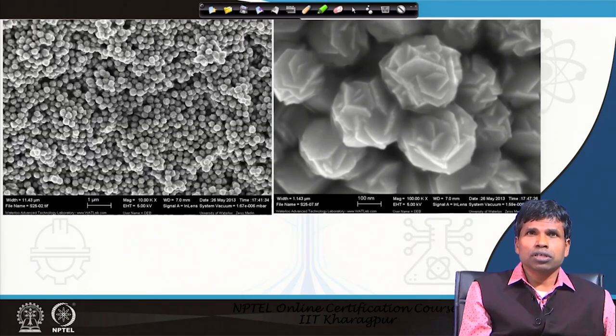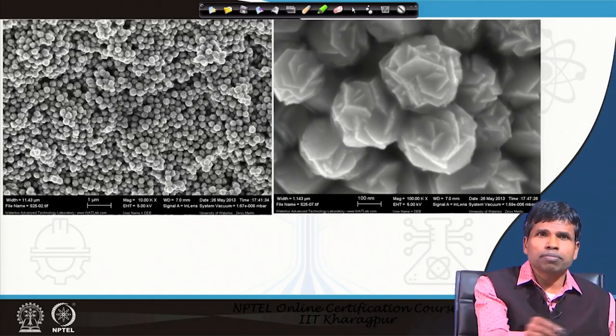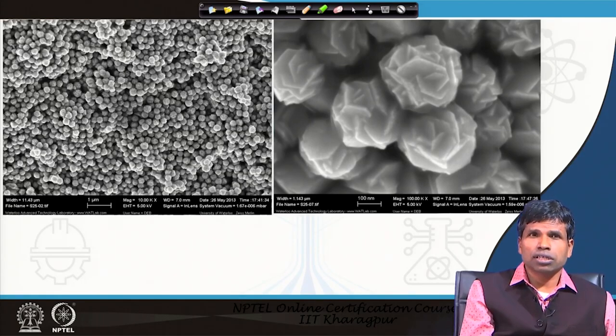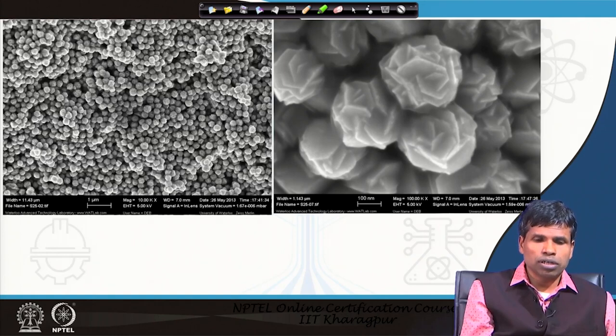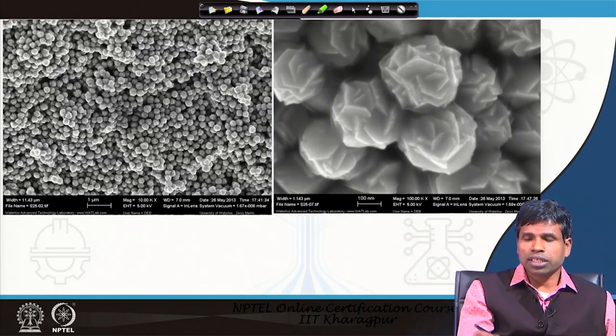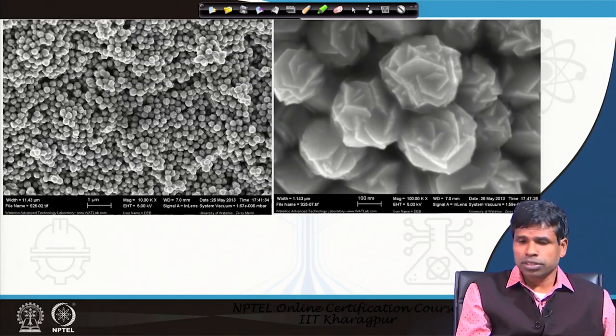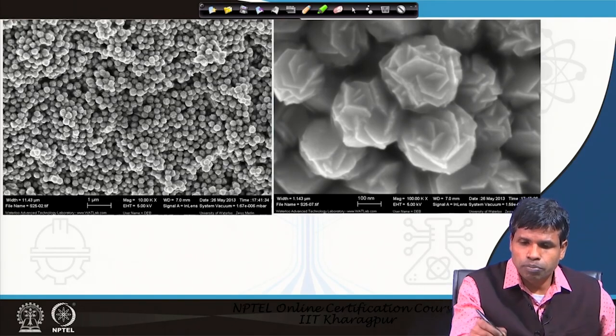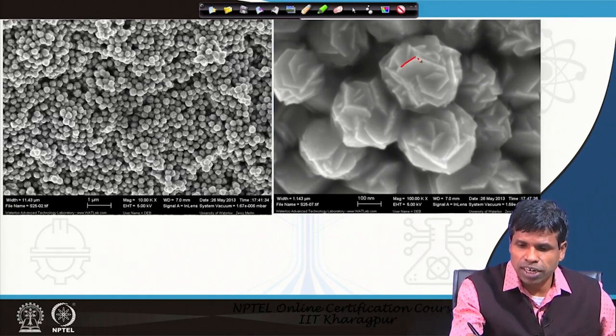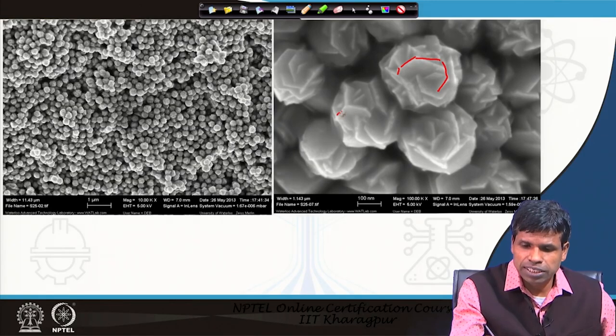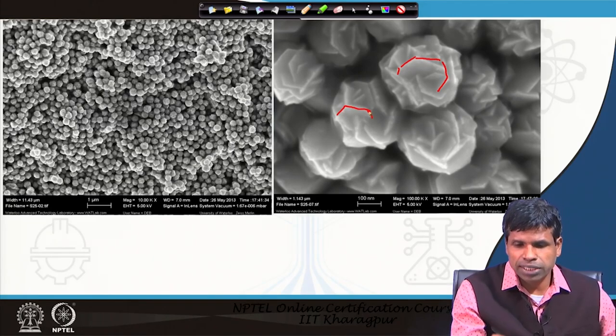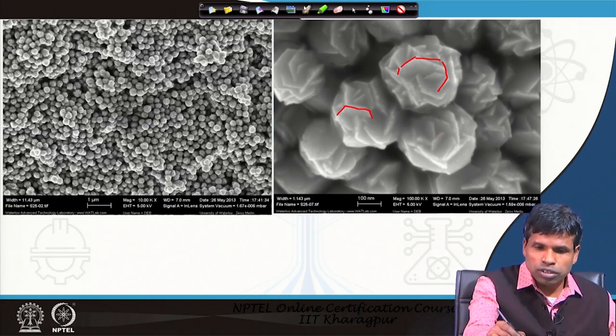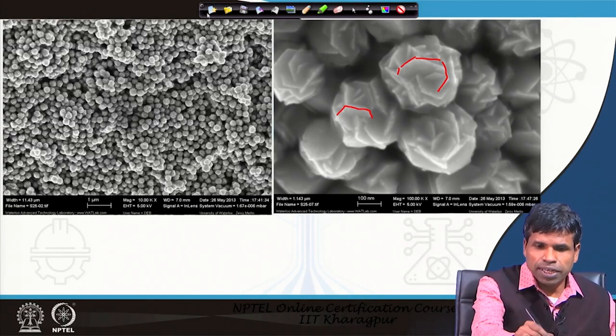In another example: on the left side you see how uniform the particles are across the sample — the brightness and contrast are presented uniformly and the total area is completely focused. On the right side, a magnified image of one or two spheres shows that individual particles are made up of plate-like structures which are hexagonal in nature. These individual spheres are formed from hexagonal thin sheets or plates that come together to produce a spherical structure.